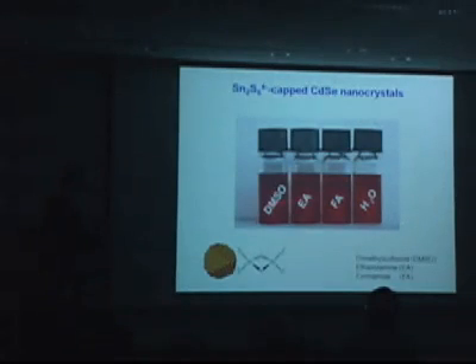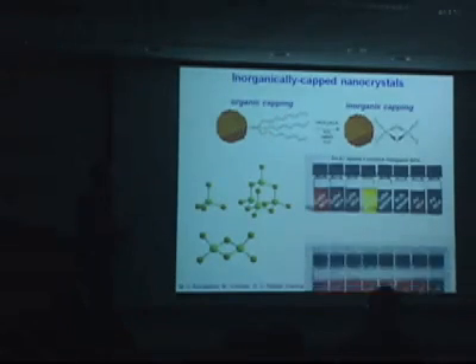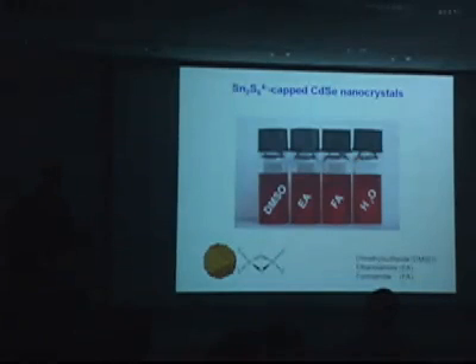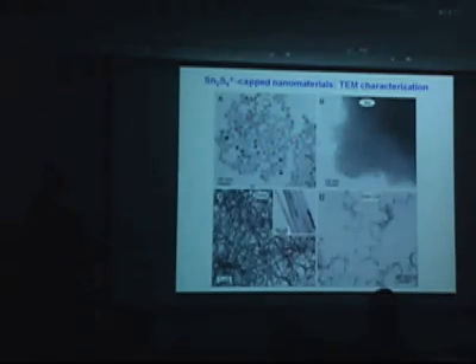They form perfectly stable colloidal solutions. In this case, we change the type of colloidal stabilization from so-called steric stabilization that we have in systems with organic ligands to electrostatic stabilization. Electrostatic stabilization is provided by attaching charged species to individual nanoparticles, and they prevent aggregation. As I already mentioned, it can be used with semiconductor nanoparticles and semiconductor nanowires, and it can even make stable colloidal solutions of large wires that would not be stable with original organic ligands. You can use it with metal nanoparticles. You can even preserve the ability of these structures to self-assemble. And very recently, last week, we made binary superlattices using this approach. It can be used for some complex structures.